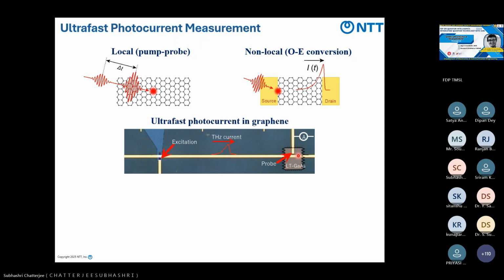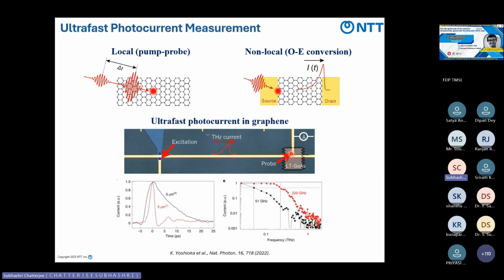So here we have a 2D material. We shine a femtosecond laser on it, and the photocurrent travels through a waveguide. With the same laser, with a time delay, we probe the signal from a low-temperature-grown gallium arsenide photoconductive switch. Then we get this kind of very fast signal from only this material.